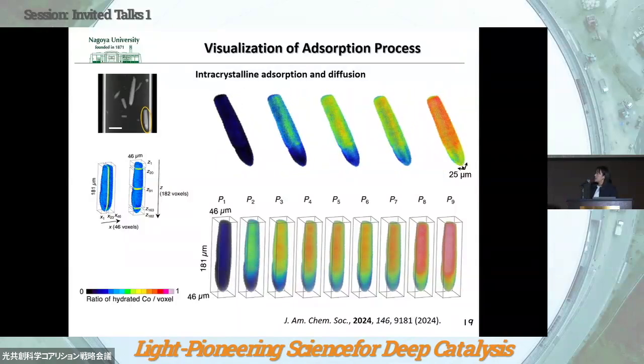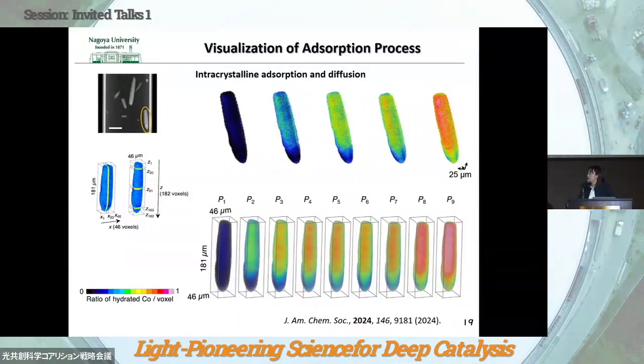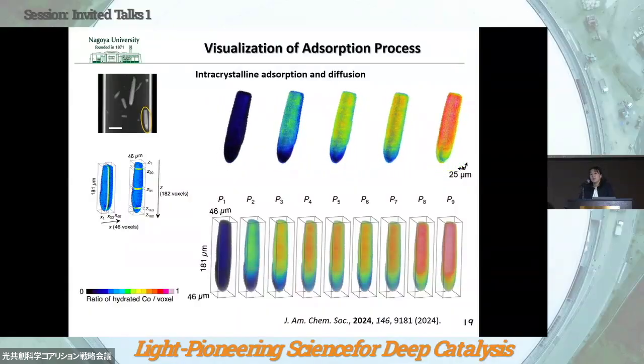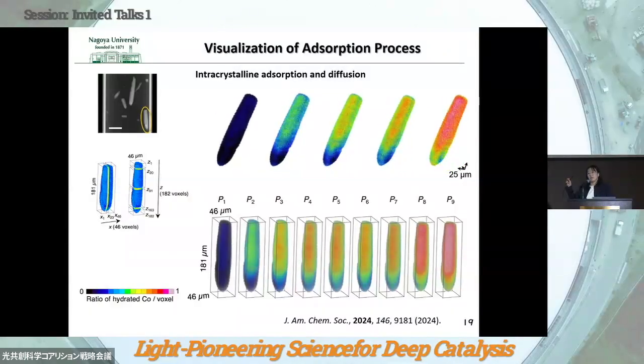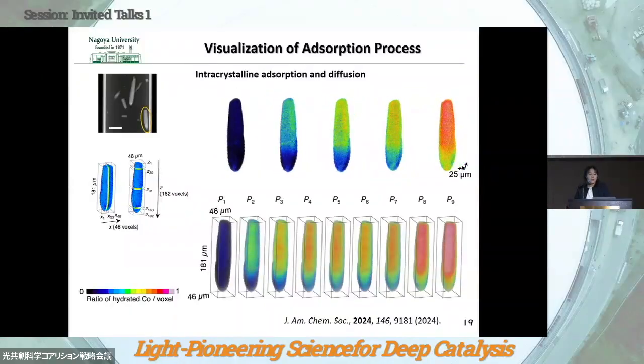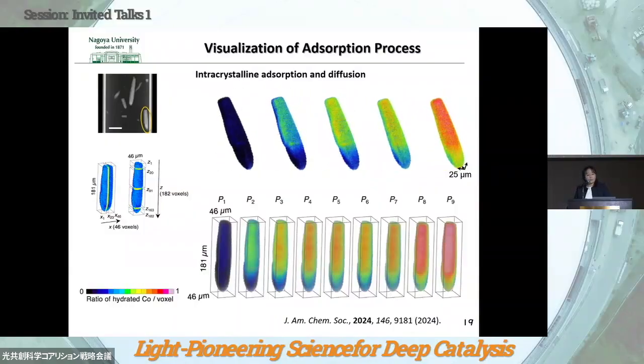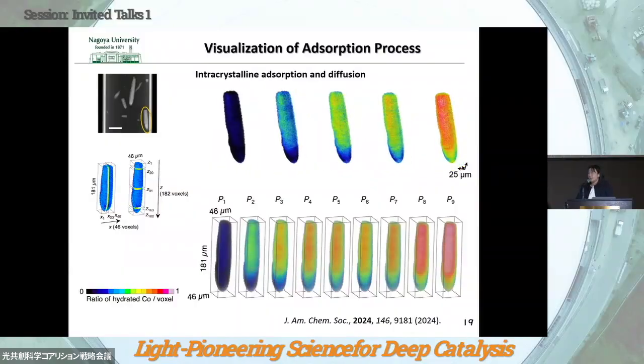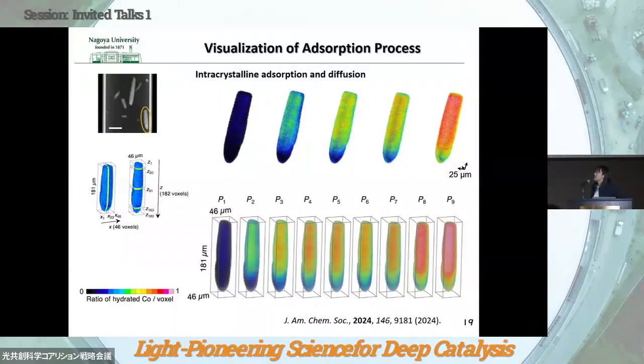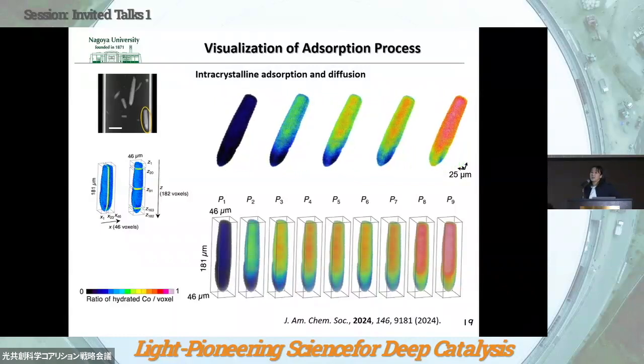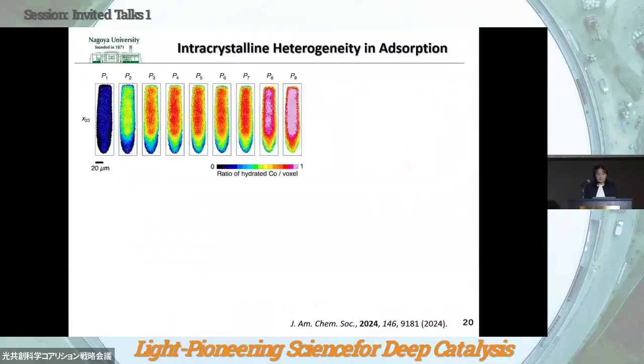And this is an initial state, and you can see the change in the color, which means the ratio of hydrated cobalt species. So at the beginning, all cobalt is an unsaturated site without any coordination of water molecules. And when we expose the sample to water, the adsorption and the diffusion proceed inside the crystal. And we can see the change in the color when we increase the relative pressure of the guest molecules for in situ measurement. And this kind of measurement shows us the change in cobalt hydration in the real crystal.